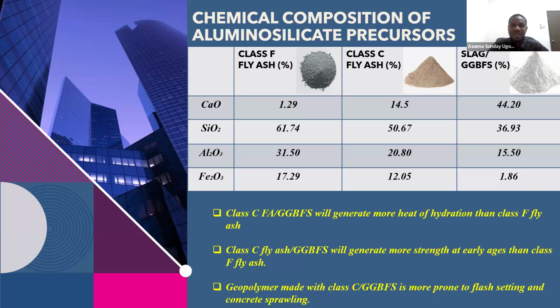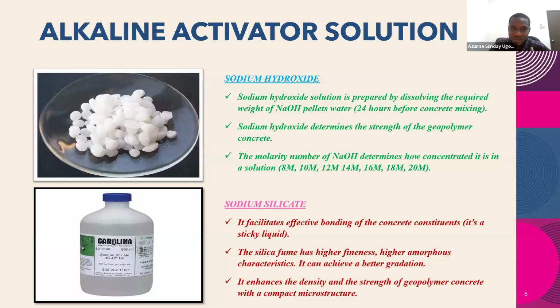The setting time is very fast, which is what has made the concrete not very practical. The setting time in some cases is even less than 10 minutes. So you will understand that more in the long run. That setting time is more of a problem when you use class C fly ash or the slag, GGBS, because the composition of the calcium oxide in class C fly ash and GGBS is very high. So it accelerates the setting time of the concrete. So that being said, I will now go into the alkaline activator solution or the alkaline solution.